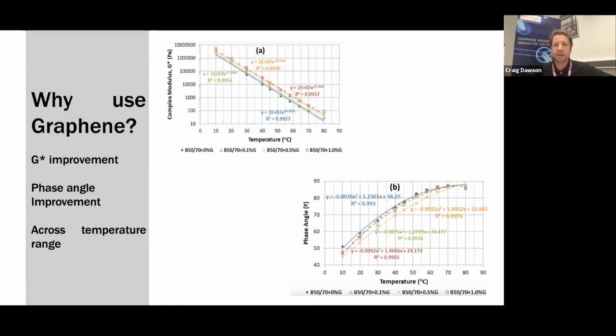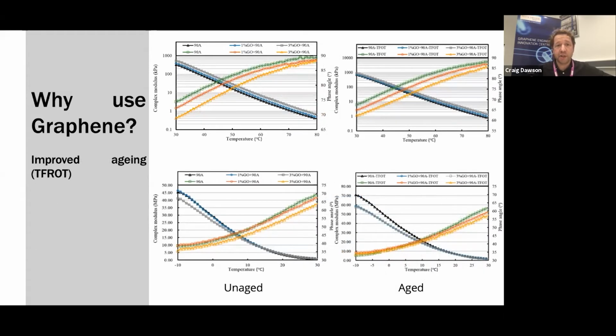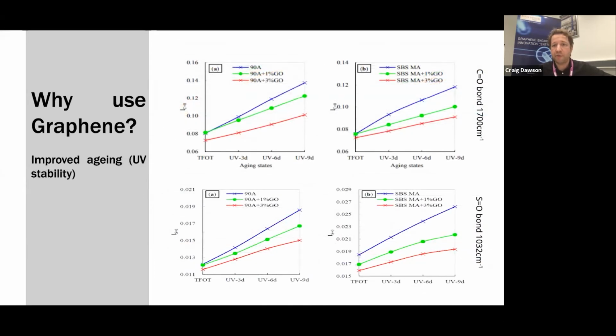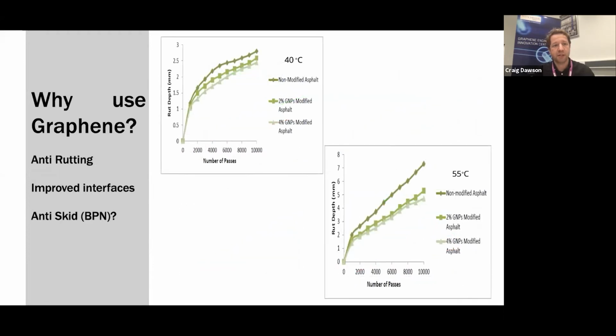That we are getting improvements across the entire temperature range. We also see this across the entire frequency range. We see improved aging, so thermal aging. We see improvements there. We see improvement in UV stability. I'll explain these a little. These are infrared analysis, looking at specific peaks around carbonyl and sulfoxide growth. We see that the growth of these peaks occurs when we get UV degradation. That is subdued by the use of graphene within that bituminous system.